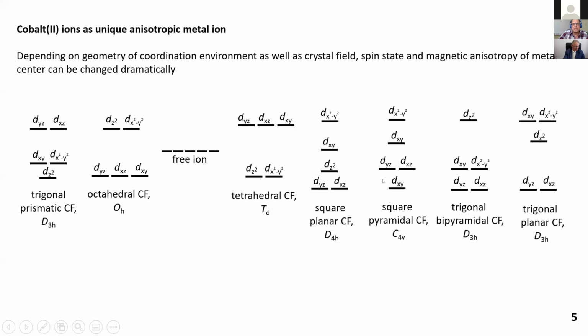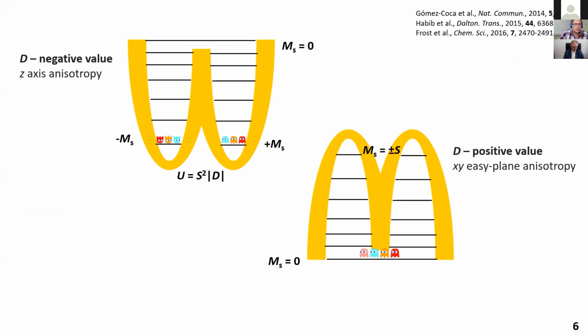And its magnetic anisotropy is very important for the realization of single molecule magnet and single ion magnet properties. It depends on its environment, coordination number, ligand field, and so on. So it's a very effective ion for preparation of compounds with unique magnetic properties. For single ion magnet properties, the zero field splitting parameter D should be negative. It determines the barrier between two stable states. A positive D value results in no out-of-phase signal in zero-field DC experiments, since it comes from easy-plane magnetic anisotropy with only one stable state.